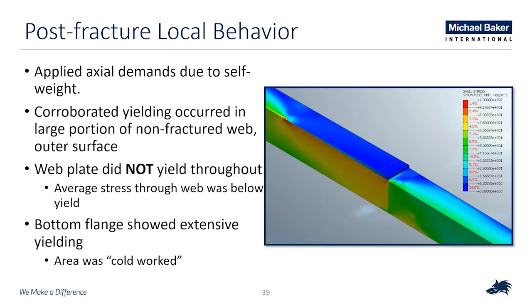Okay. So regarding the post-fracture local behavior, the first thing is that after applying axial demands and self-weight, we were able to corroborate that significant yielding developed, particularly on the outer surface of the inboard web plate. Pretty much throughout the outer surface, the yielding would have been reached over much of the height of the plate. However, when we look at the through-the-thickness average value, we see that the average stress through the web was actually below yield. If we look at the bottom flange, you can go to the next slide.